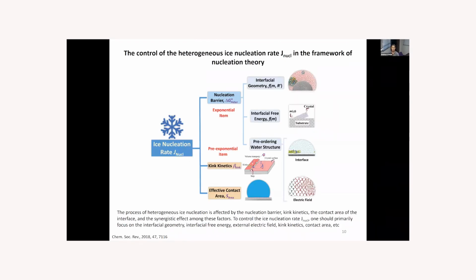So the ice nucleation rate is depending mostly on the nucleation barrier, the kinetics, and effective contact area. The parameters of the nucleation barrier that we can control are the interfacial geometry, interfacial free energy, and preordering of the water structure, by introducing interfaces that can preorder the water molecules on the surface or introducing an electric field. I will show you examples of all of this after.